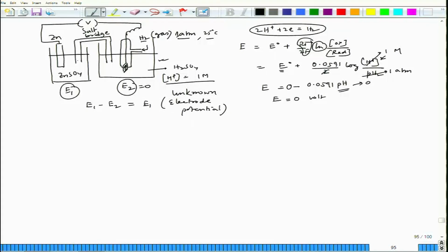Now, if we take some metal, and why do we take platinum? Because on the platinum surface, the exchange current density is around 10 to the power minus 2 to 10 to the power minus 3 ampere per centimeter square, which is considered to be very, very high current density.